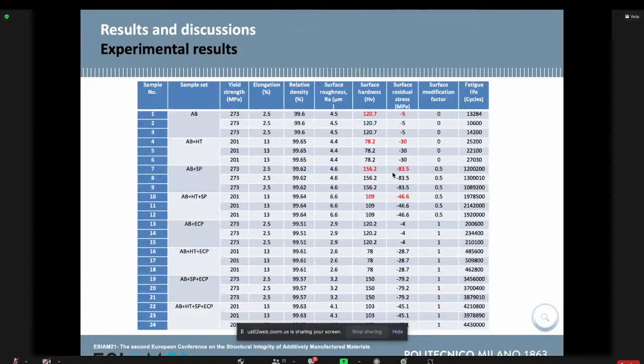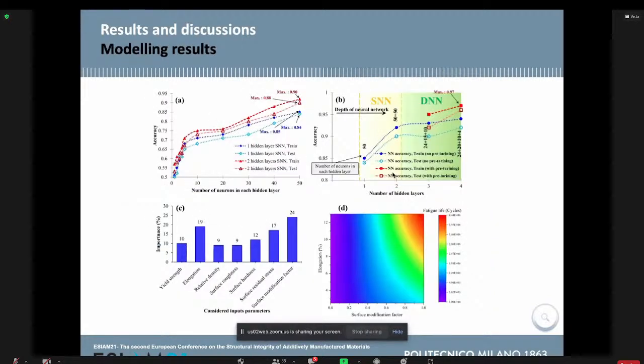And then we develop a neural network using these data. It was found that by increasing the number of neurons in each layer, we can get higher accuracy. Also, although we had a small data set of 24, we can reach 97% accuracy by using pre-training with a stacked autoencoder, which shows that we get very high accuracy.